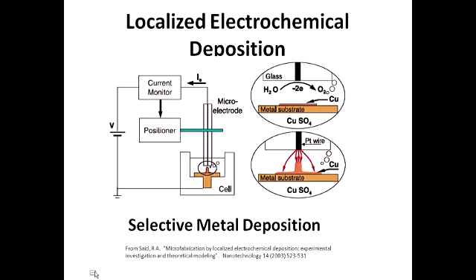And also, when we have copper here, there are also oxygen and something else, and that maybe makes some contamination, and we couldn't have a very good deposition layer. But with our method, we use physical vapor deposition. We do not have anything else. We only have metal atoms, not anything else. And the controlling of the process and also the cleanness, there is no contamination, that's easier.